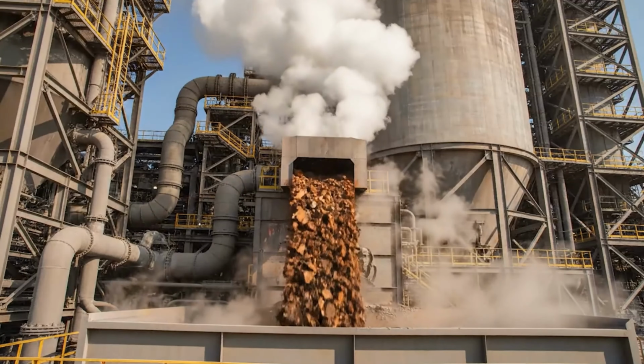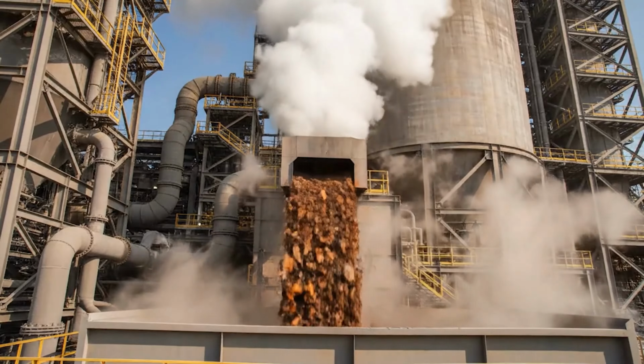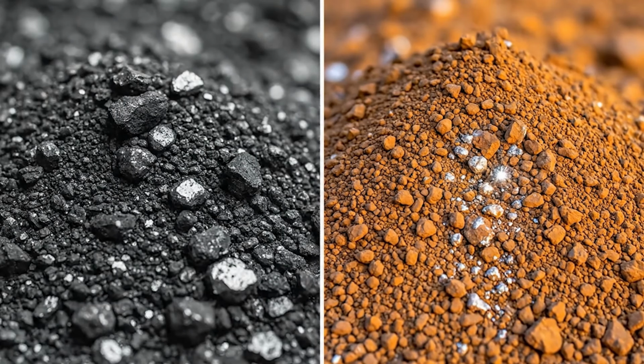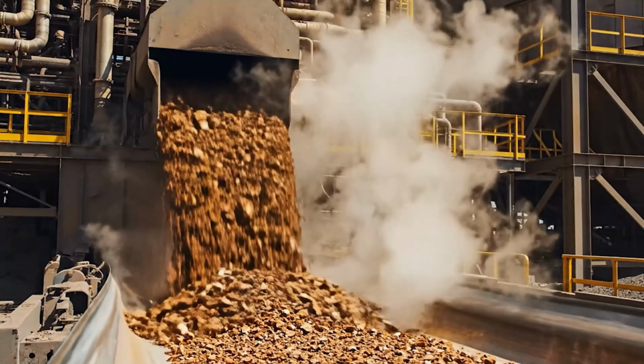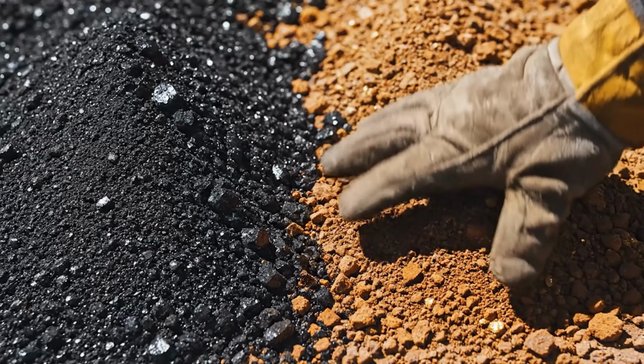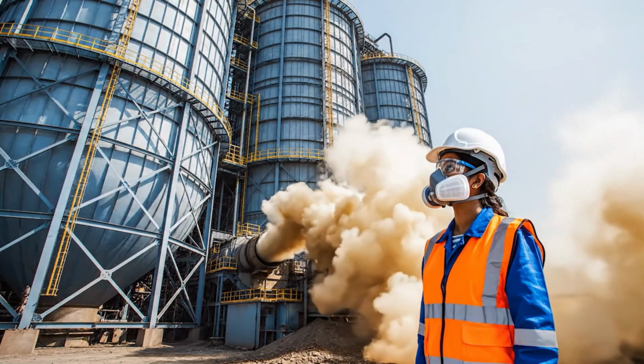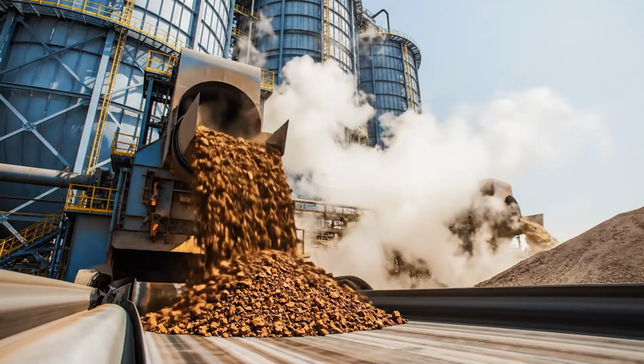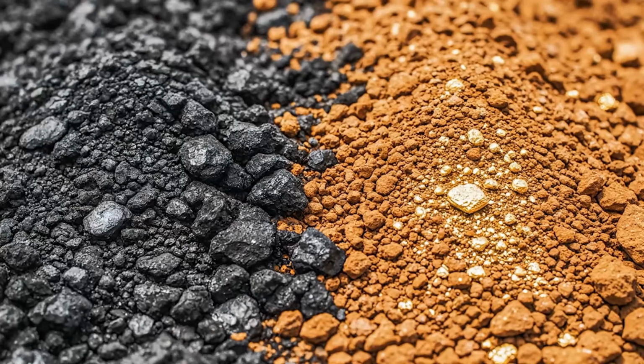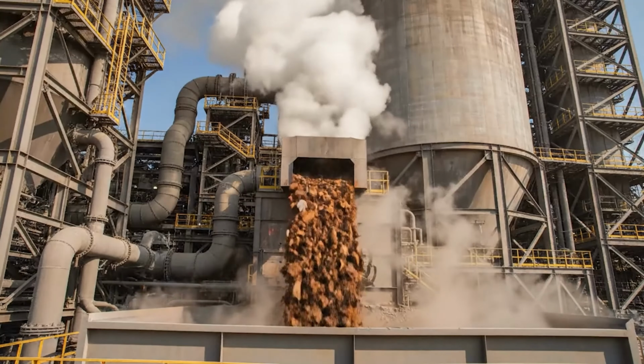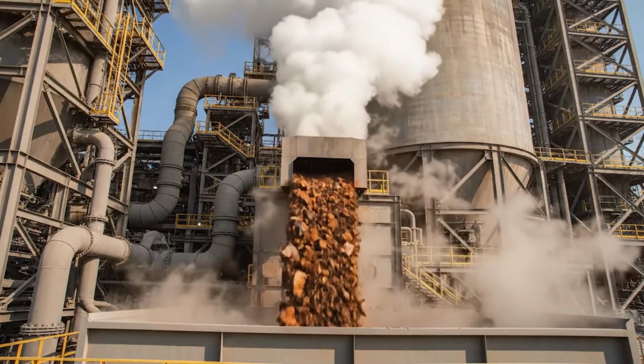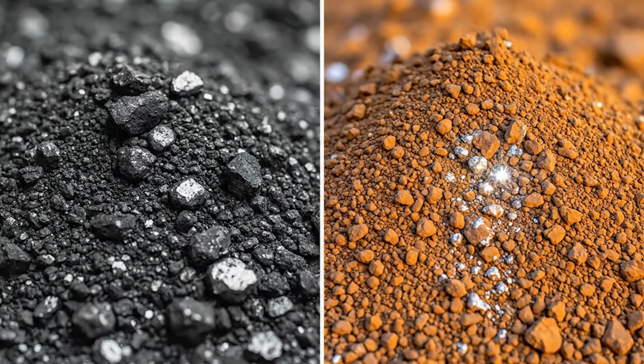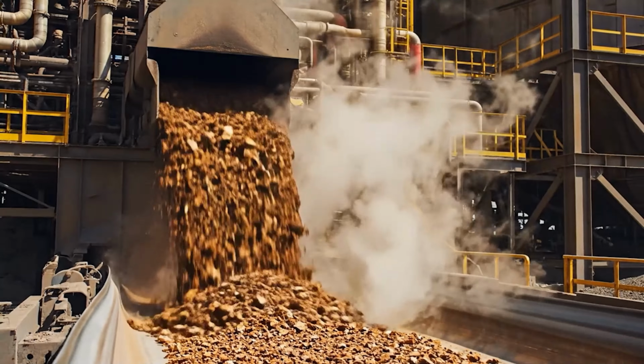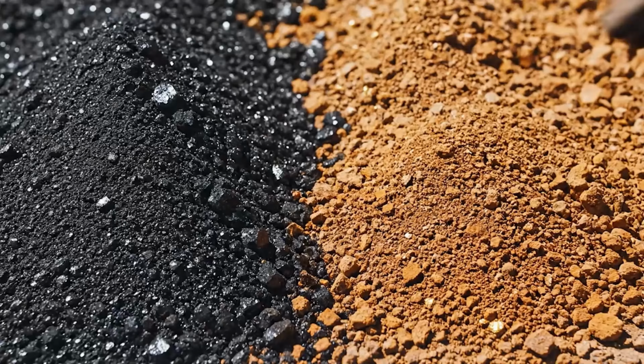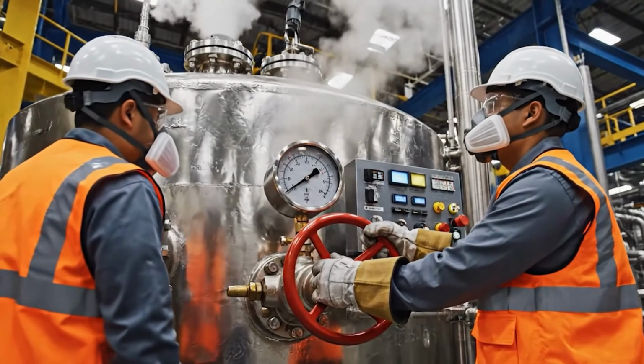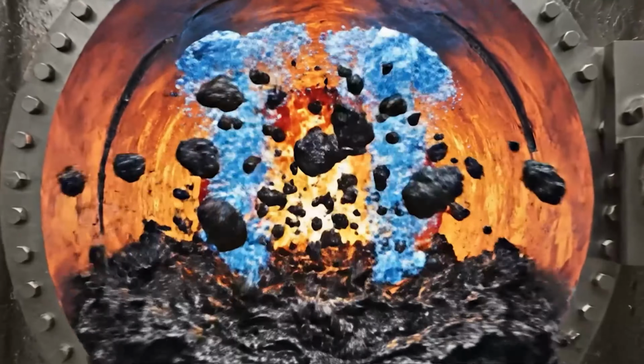The roaster is a beast. Imagine a rotating drum 50 meters long, glowing red hot inside, processing hundreds of tons per day. The sulfur dioxide is captured by scrubbers and converted to sulfuric acid as a byproduct. What comes out is called calcine, a crumbly, oxidized material where the gold is now exposed and ready for cyanide leaching.